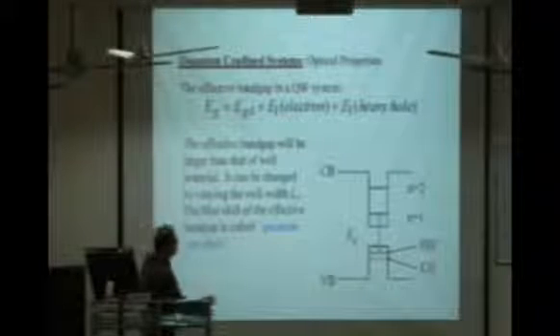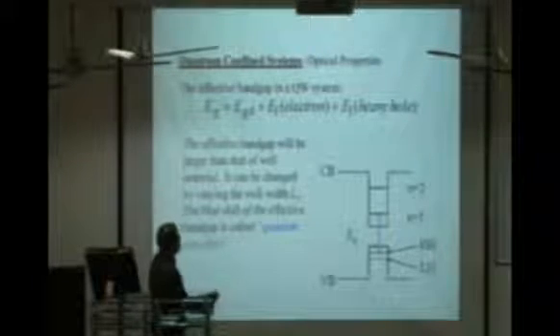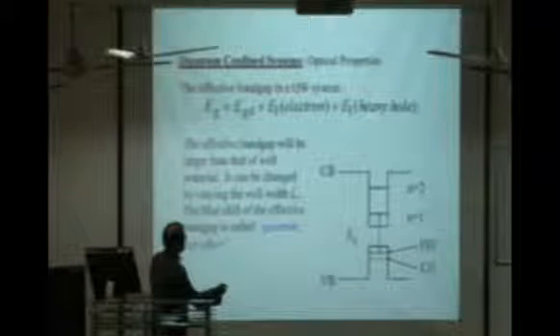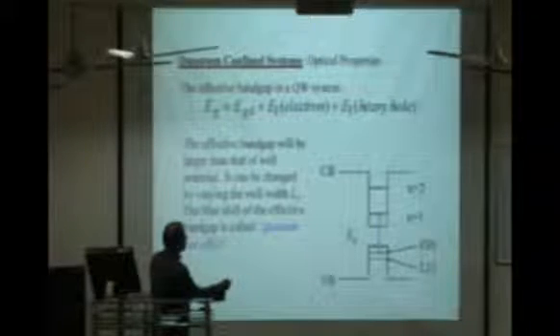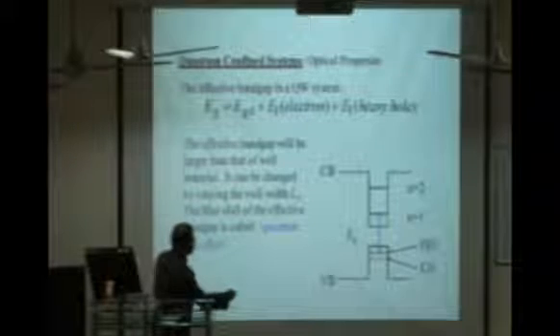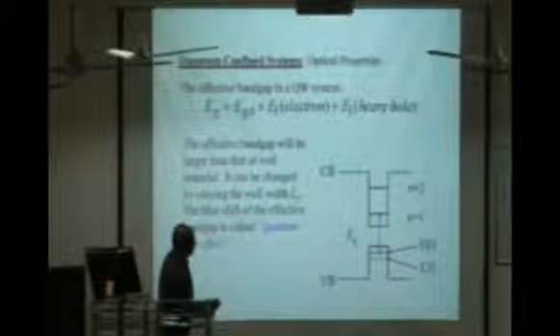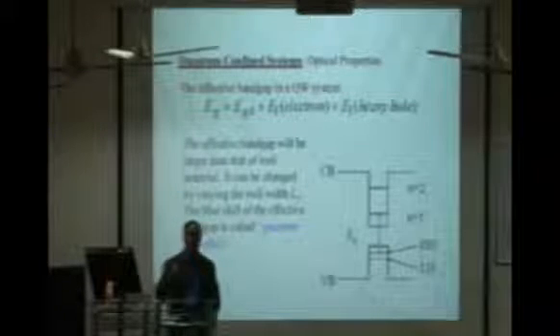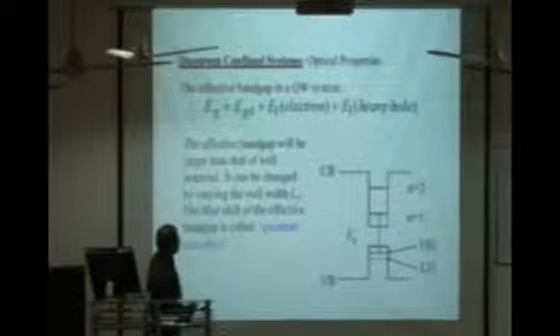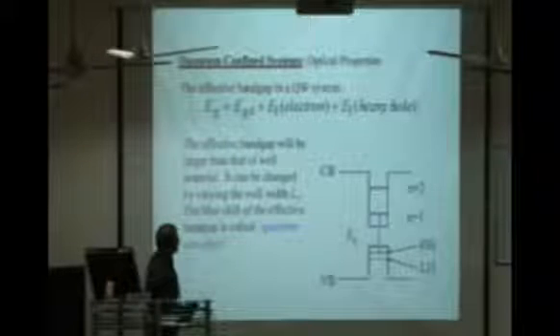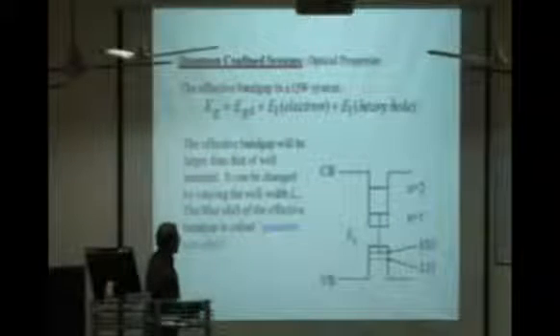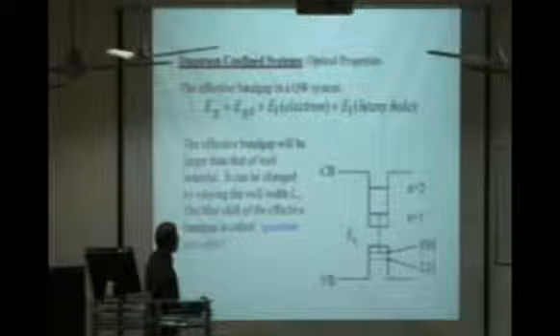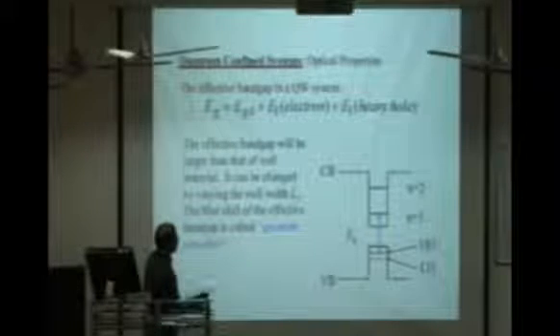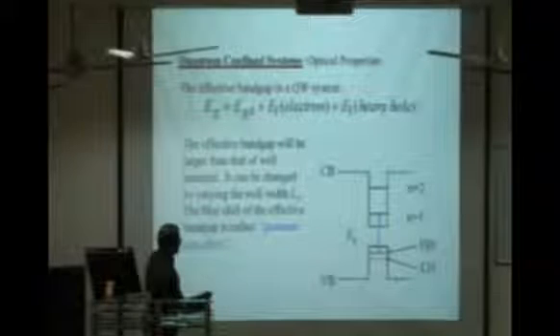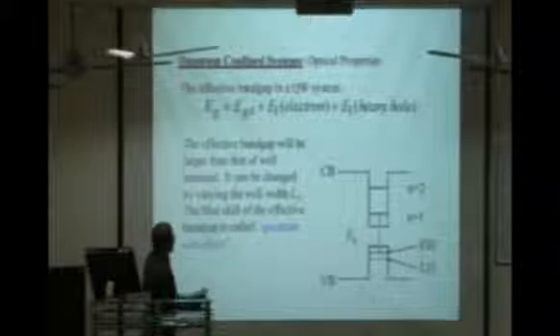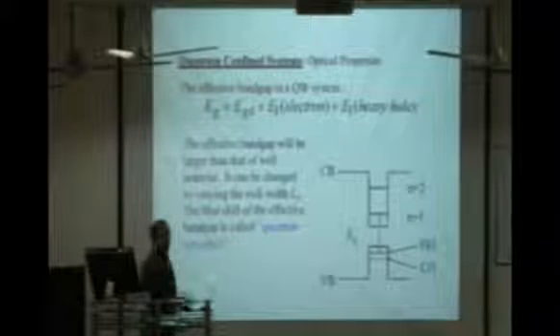And if the width of the well is low enough, below the de Broglie wavelength, we get a quantization of energy. As you see, this is the ground state energy for the electron, and this is the ground state energy for the hole. In fact, the valence band is more complicated. You have got heavy holes, light holes, spin-orbit split holes, so a lot of complicated things are there. But we take the heavy hole as it probably has the lowest energy, so that is the ground state energy. Initially we started with a semiconductor with a band gap Eg, and because of the quantization, the band gap has gone up like this.